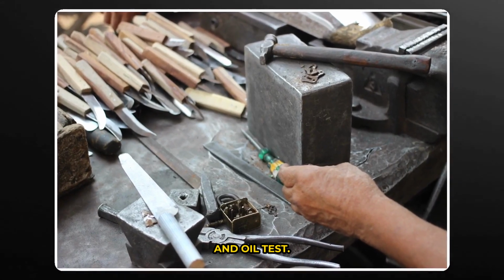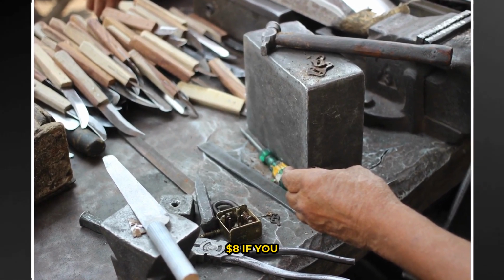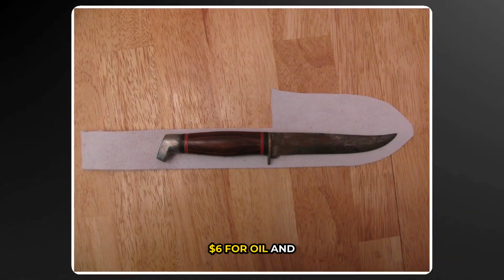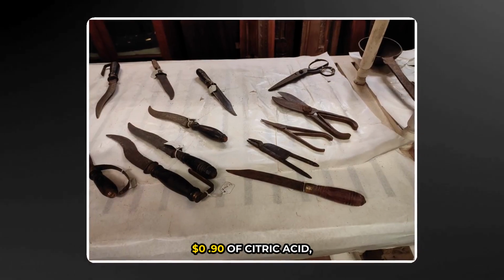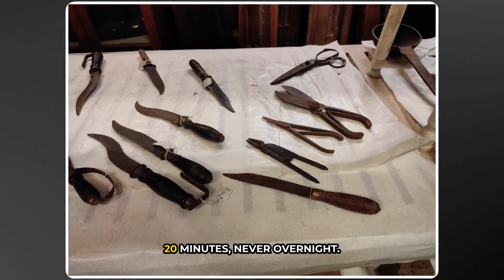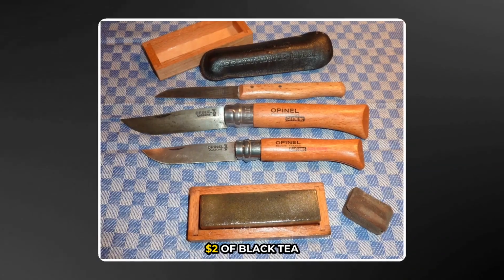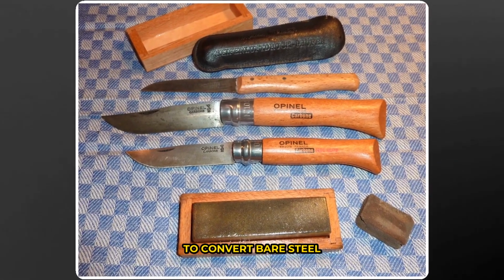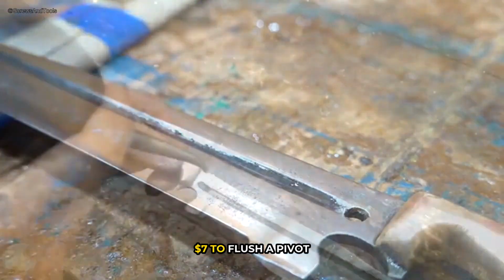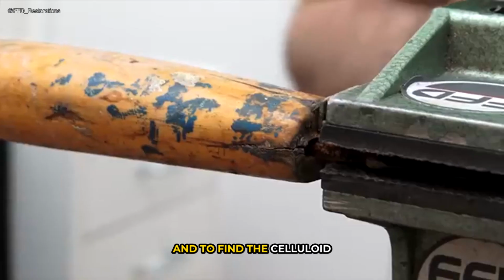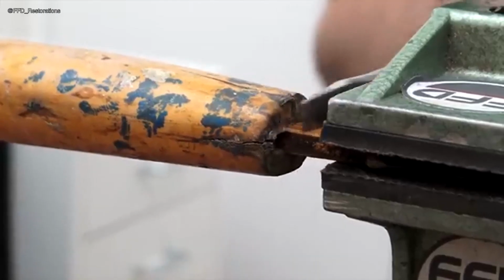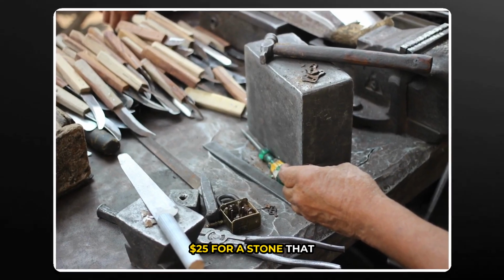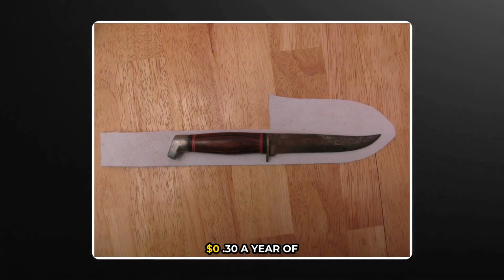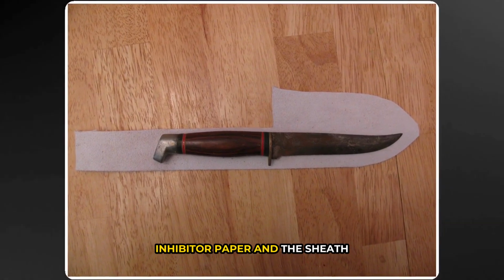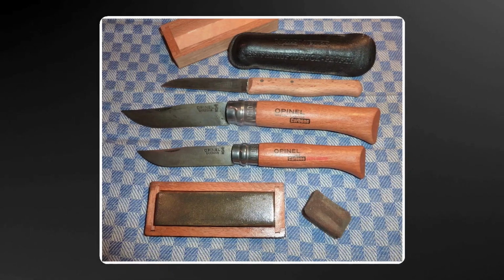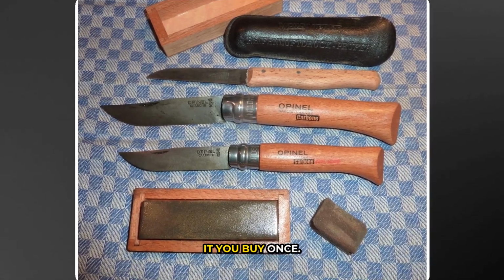$3 for the rag and oil test, free to read the tang, $8 if you want the loop, $6 for oil and fine steel wool, 90 cents of citric acid, 20 minutes, never overnight, $2 of black tea to convert bare steel back to black, $7 to flush a pivot and to find the celluloid before it eats the collection, $25 for a stone that cannot burn an edge, 30 cents a year of inhibitor paper and the sheath comes off tonight, $61, and most of it you buy once.